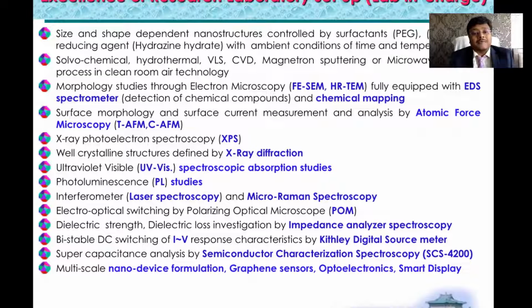So after the chemical synthesis process, we go for characterization. First we do FESEM, field emission scanning electron microscopy, then we do high resolution transmission electron microscopy, and what kind of materials are there is detected by EDX spectra. Then we can go for chemical mapping also, and surface morphology is analyzed by AFM, and we can also measure the surface current, how much current passes through the surface, by conducting mode AFM, CAFM.